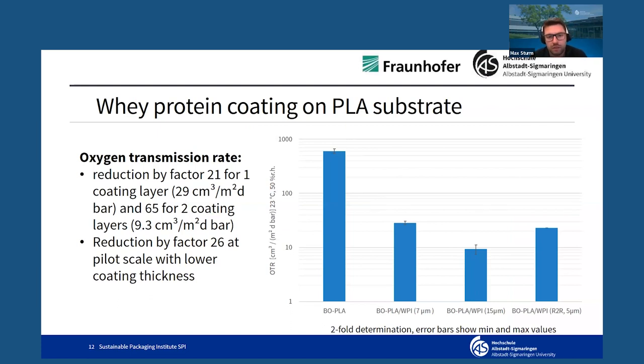So as the whey protein based coatings are mainly used for oxygen barrier, this is the first property we analyzed here, for example, for PLA substrates. Please keep in mind, this is on a logarithmic scale. You can see here for the PLA film itself, the oxygen transmission rate was measured at approximately 600 cubic centimeters per square meter day bar. And after application of a whey protein coating with just 7 micrometer thickness, this was reduced to about 30 here at lab scale, and could even be reduced to approximately 10 with a second coating layer, so for overall 15 micrometer coating thickness. After this, the coating was upscaled to pilot scale coating.